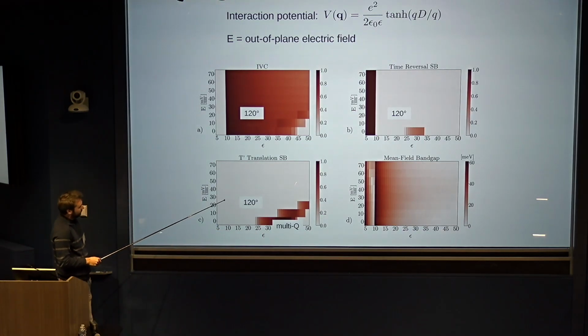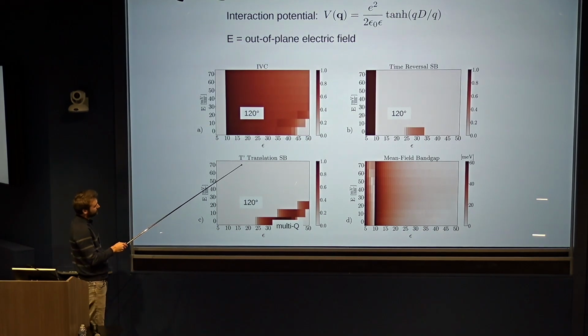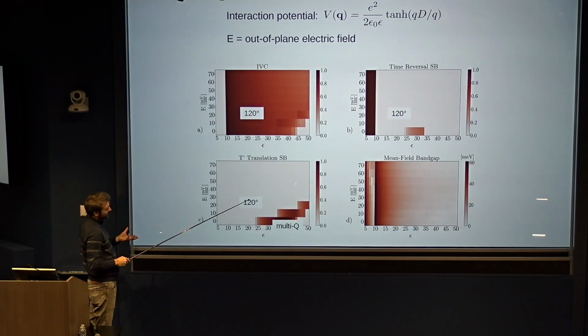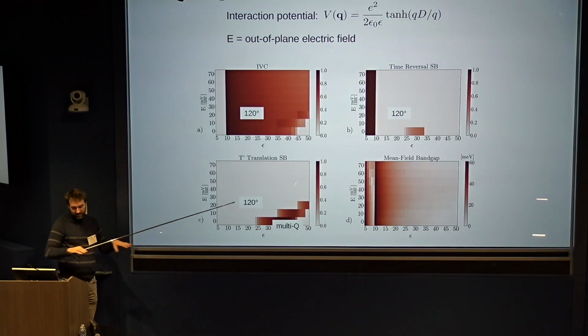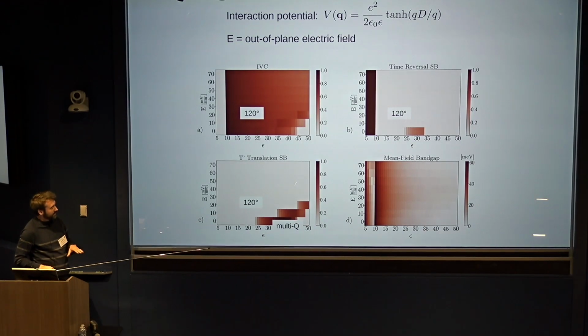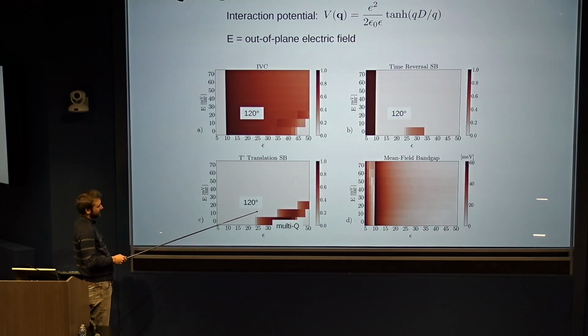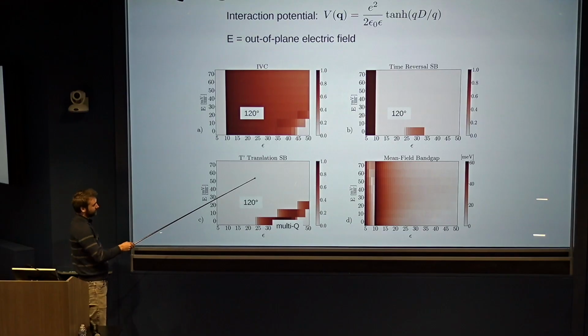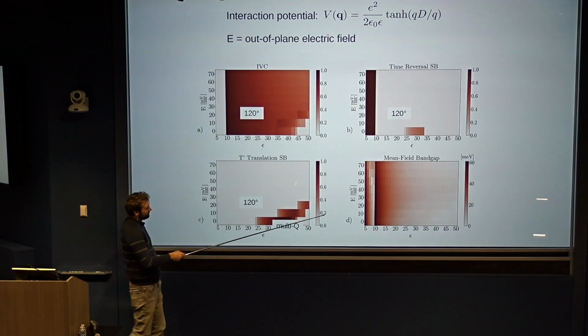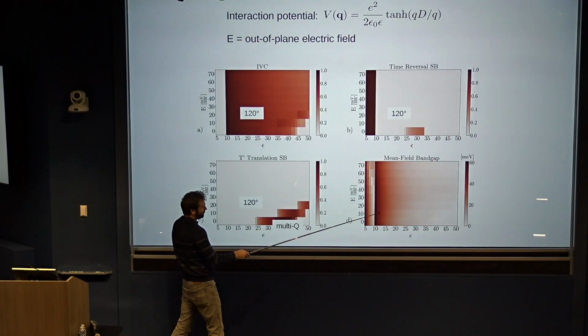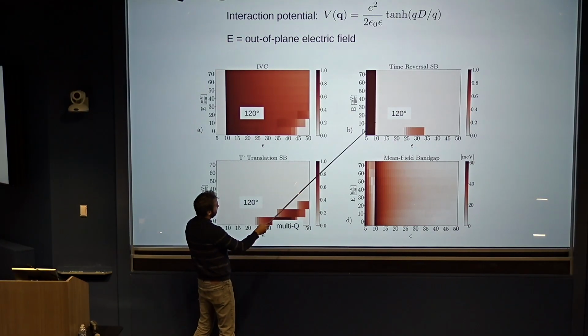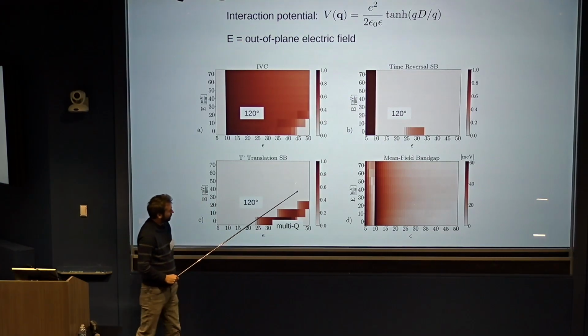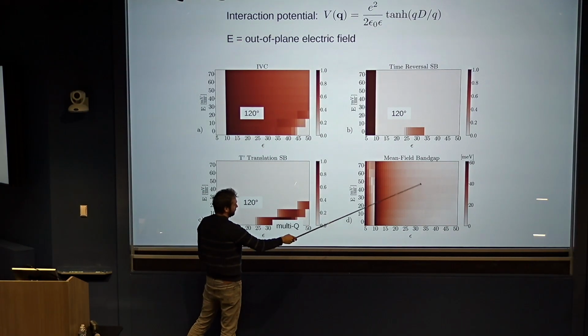The bottom left is an order parameter for an unconventional type of translation symmetry, where you translate your lattice and then rotate the spins by 120 degrees. Again, this is a symmetry of the 120-degree AFM, so the order parameter is 0 here. And this is the mean field band gap, just to show that almost everywhere where we have magnetism, so where we have a non-zero order parameter, there is a band gap, at least at the mean field level.